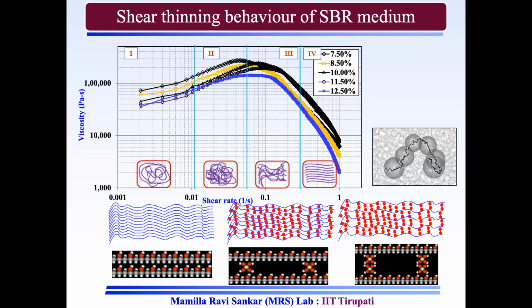If you see among the curves here, now observe all the curves, and you see here 7.5 plasticizer to 12.5 plasticizer. As I said, polymers are high molecular weight materials and plasticizers are low molecular weight materials. Okay, if you see from 7.5 to 12.5, the viscosity is reducing. Why is the viscosity reducing?